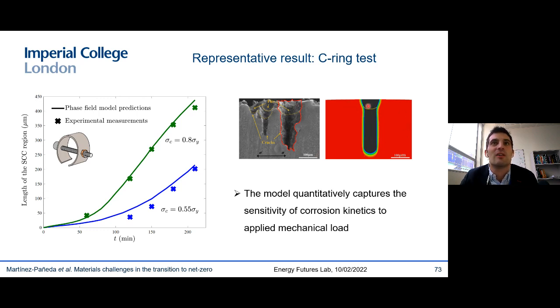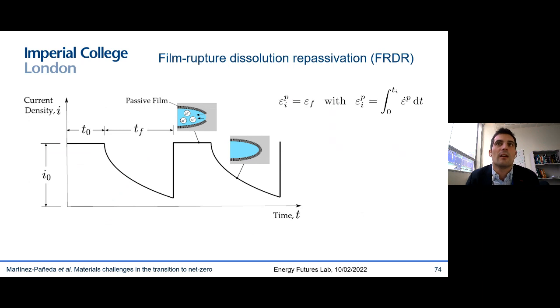On the right, you can see on the same scale how the corrosion defect morphology prediction agrees very well with experimental observation. We focus only on one pit, but we could model all of them. And on the left, you can see how our predictions of corrosion length versus time for different load levels compare very well with experiments. And another thing that we have done is to extend the model to account for the presence of a passive film and the film rupture and repassivation processes that are relevant to most material environment systems.